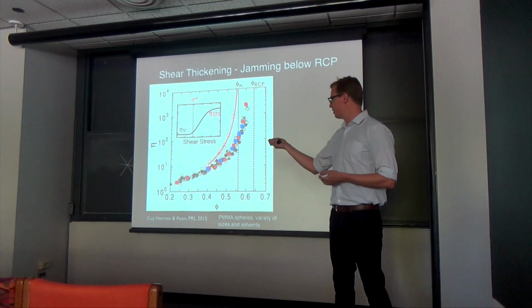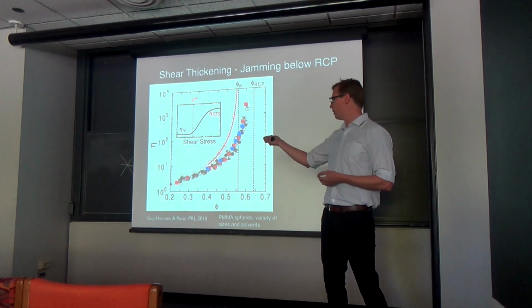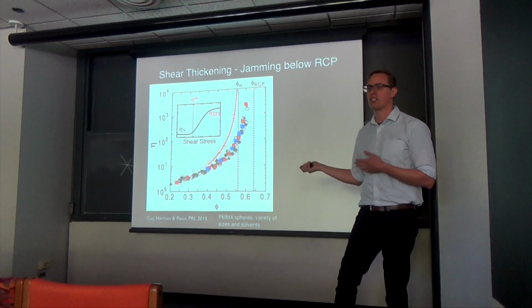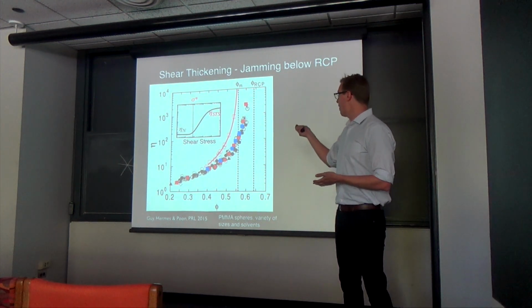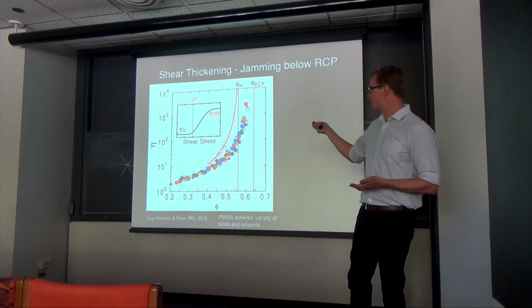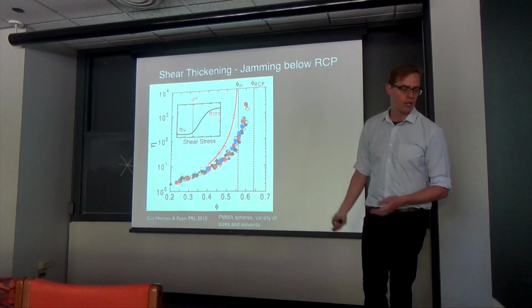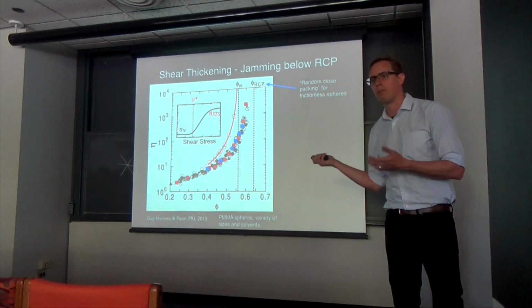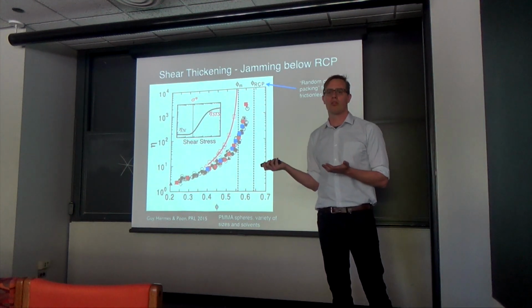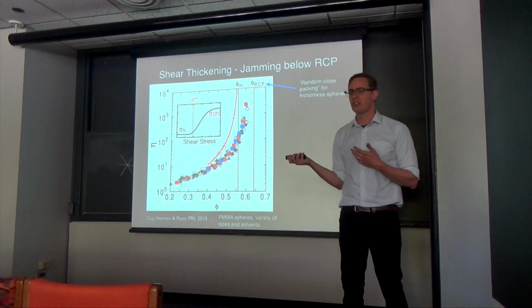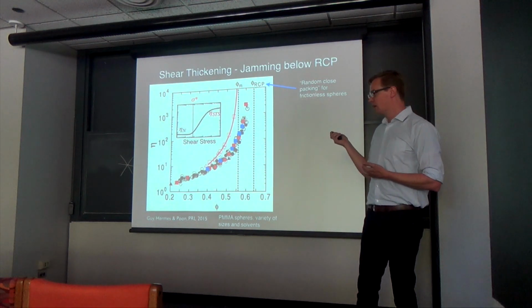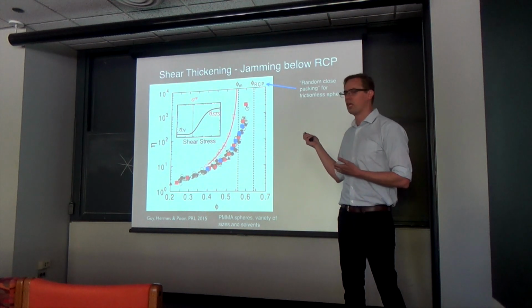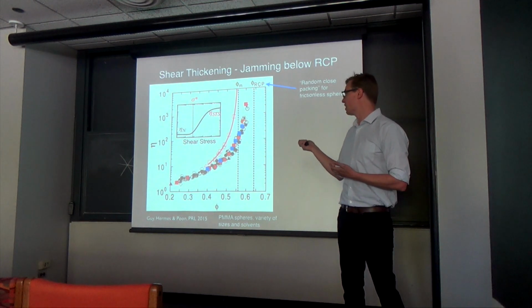So if you look at this Newtonian plateau here, you have the viscosity increasing with the volume fraction, with the concentration of your particles, and then it diverges, looks like it's diverging around 60-some percent. So this is very close to what you might expect around random close packing for hard spheres. So it's easy to get a handle on, or think about why the viscosity is diverging here.